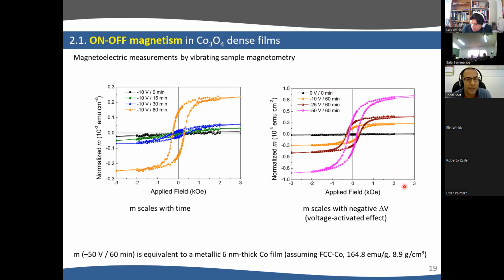So just here to show that the things can be modulated with time, keeping the voltage constant. For example, here the longer the time, the larger is the magnetization. And for example, here you can see progressive increase of magnetization with time. Or you can keep the time, for example, to 1 hour and just increase the voltage you apply. You can see that also the magnetization scales with the voltage. And actually, to have an idea, at minus 50 volt for 1 hour, the moment we generate is equivalent to a 6 nanometers thick cobalt film. So we started from 100 nanometers thick. It means that we have a 6% conversion from cobalt oxide to metallic cobalt.